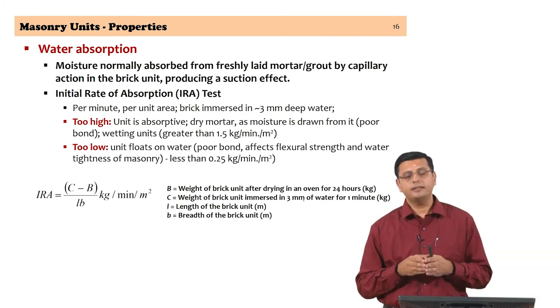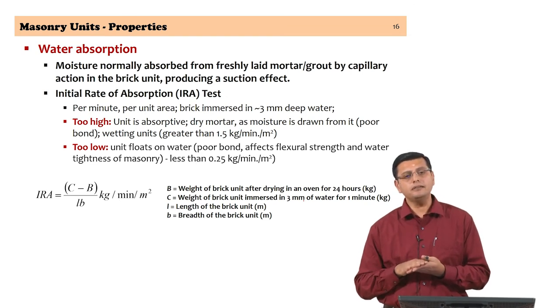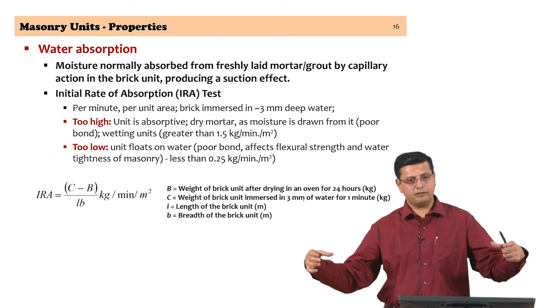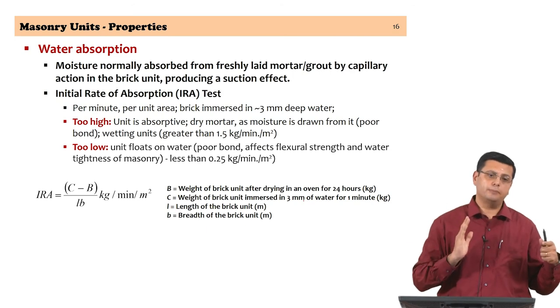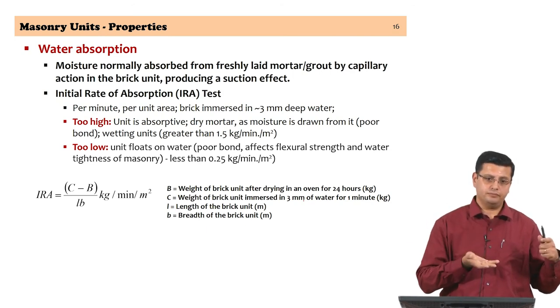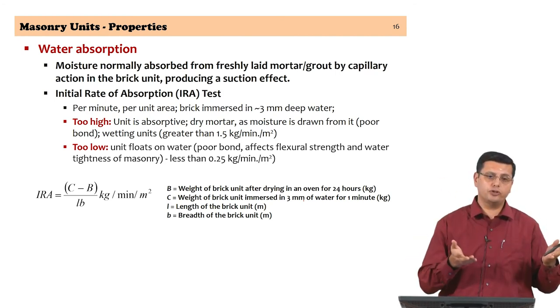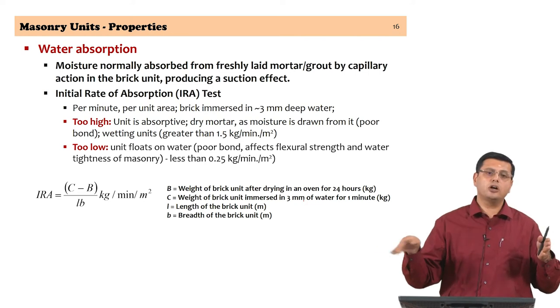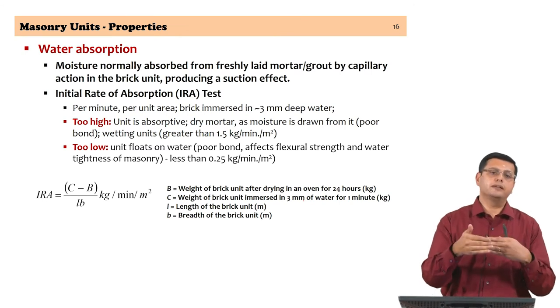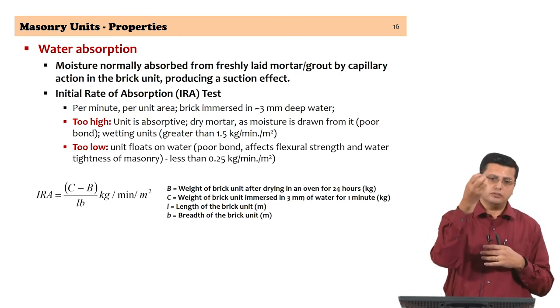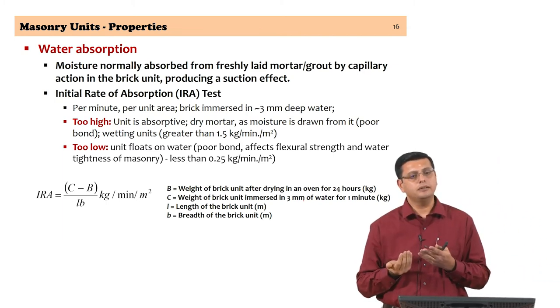The reason for 3 mm of water is that the test tries to replicate site conditions where mortar is placed on a brick course. We are interested in the surface absorbing water — the surface in contact with the plastic mortar is only the top or bottom surface. So we restrict ourselves to 3 mm, and of course there is capillary action with the wet mortar in contact with the brick unit.